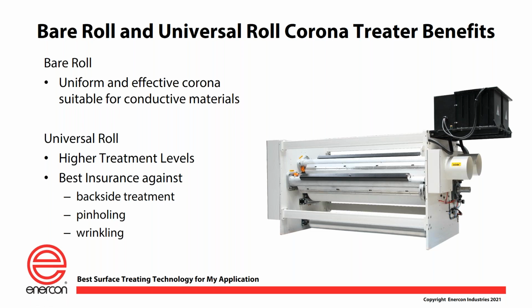So up next are the bare roll and universal roll systems. They're sort of twin brothers, so to speak, and they both have the same feature set. They provide very uniform and effective corona. They're suitable for everything, whether it's conductive or non-conductive. The universal roll sort of ups its brother a little bit because, depending on the material, you can get higher dyne levels with it based on the same output power as compared to a bare roll. It also has some benefits because of that ceramic coating on the roll. It really is a good insurance policy against things like reverse side treatment, backside treatment, and any pinholing that may potentially be there. And if you have a very thin gauge film that could be prone to wrinkling, that ceramic material on the backing roll is great for that substrate. Next slide.